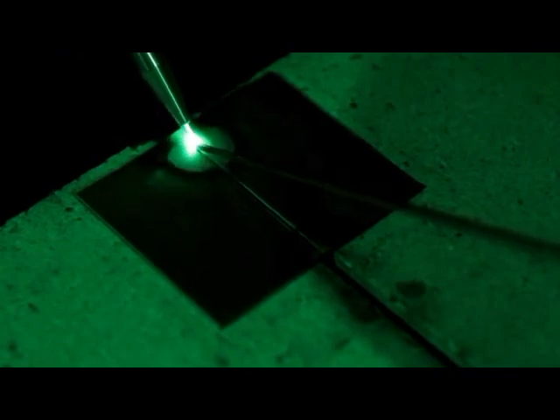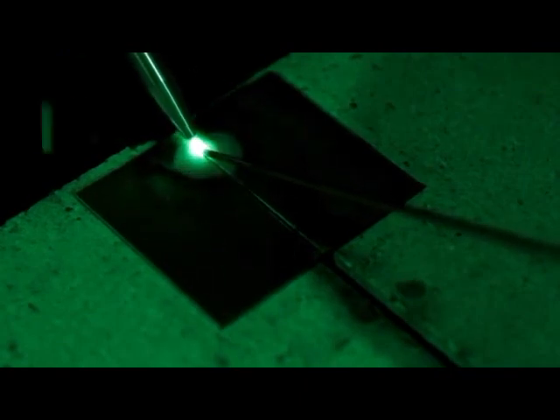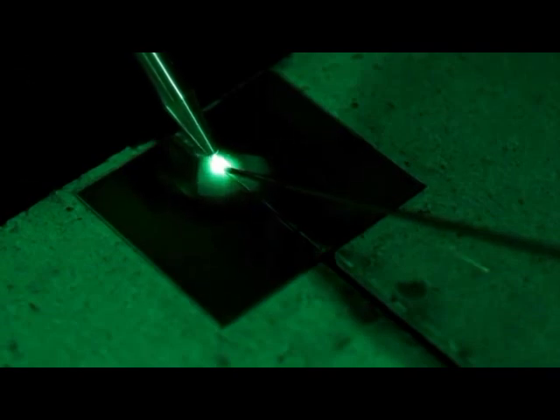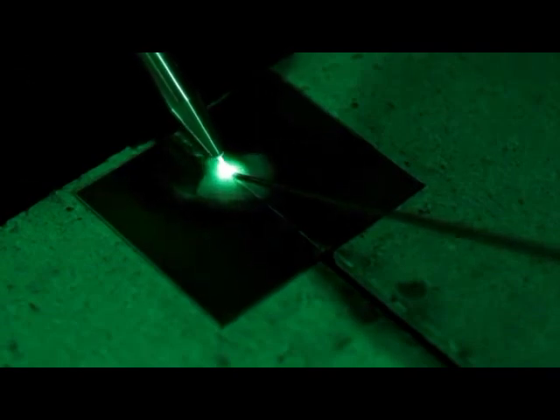Here with the steel, if you take that rod and lay it right on the metal, take that little cone and just walk up the rod, wait for it to melt, wash it right back into the puddle. Try not to let that rod pull away. Just keep it pushed into the edge of the puddle.